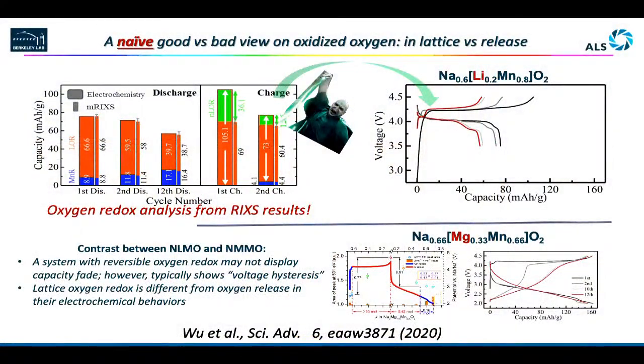However, we see another problem here. This is the charge voltage. This is the discharge voltage. The difference between the charge and discharge is huge. So what that means for a battery is you need to pour in a lot of power to charge up your battery, but when you start to use it to discharge, you drain out much, much less power. You're just wasting tons of energy. And that already indicates there's an energy barrier in there. And that's the so-called voltage hysteresis. So remember this name because we are coming back to that.